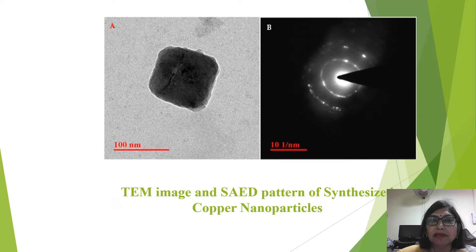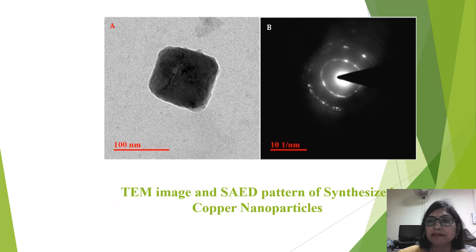The formed nanoparticles are also confirmed by TEM analysis results, which indicate the synthesized nanoparticles are in cubical shape with an average size of 40 nanometers. This is also confirmed by the SAED electron diffraction pattern. The result indicates the synthesized nanoparticles are highly crystalline.